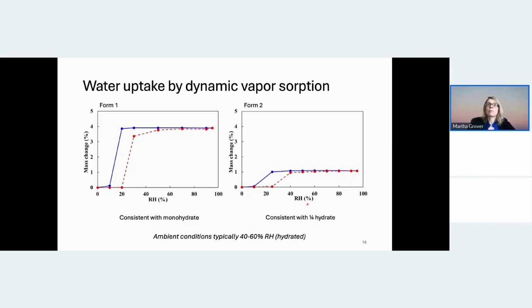However, when we performed the same experiment on form 2, we saw that it also took up water, but it took up less water. So only about a fourth of what was taken up by form 1. So this is actually very different. It's taking up water. Now, the original crystal that we made in the acetonitrile may not actually have had any water in it at all, or possibly it could have been a quarter hydrate, although the concentration is so low that that's kind of hard to believe. But in any case, it is taking up some water, but significantly less water.